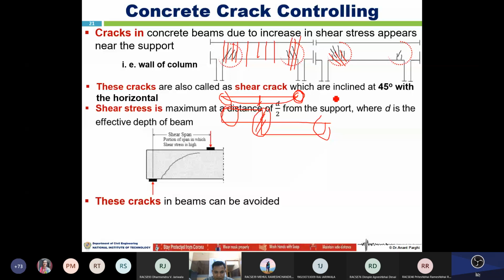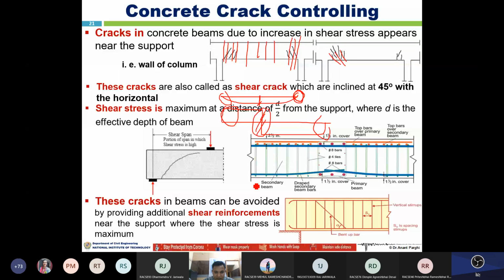The shear crack occurs within a maximum distance of d by 2 from the support, where d is the effective depth of the beam. This crack can be avoided by providing additional shear reinforcement near the support where the shear stress is maximum. For the simply supported beam, the shear force is maximum near the support, so diagonal shear cracks are going to develop here. If you provide proper lateral reinforcement near the support, you can control the cracks. Therefore we provide bent-up reinforcement in order to resist those shear stresses.